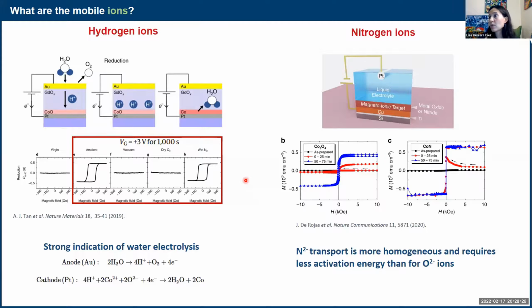And also the fact that it requires less energy. The energy barrier for the motion of nitrogen is lower than for oxygen. So that also opens perspectives for being able to use these materials with lower voltages, for example.